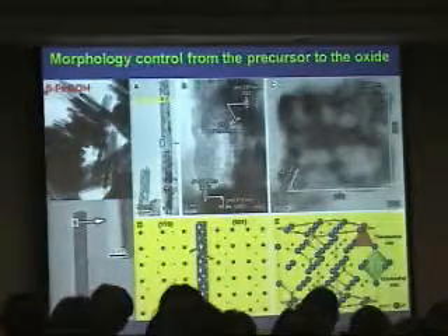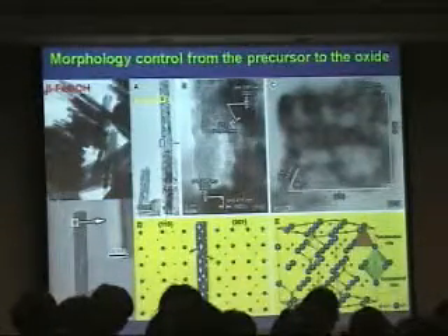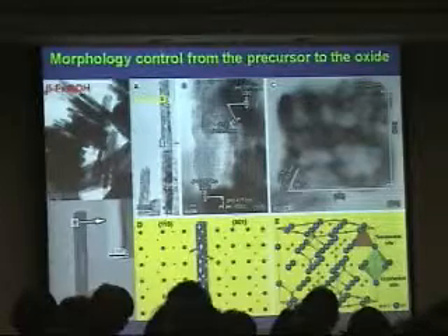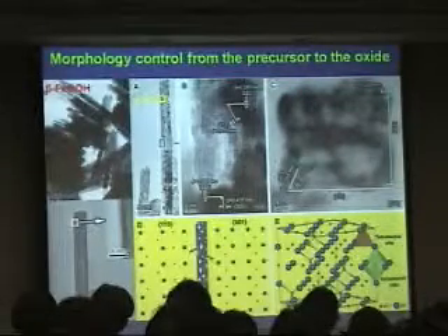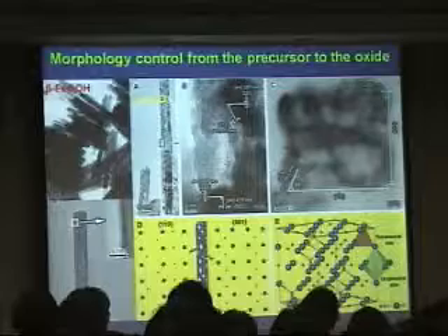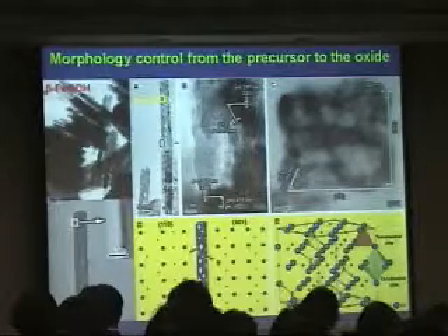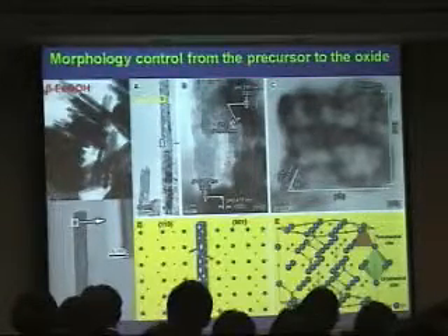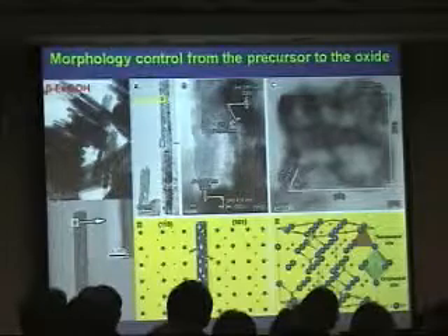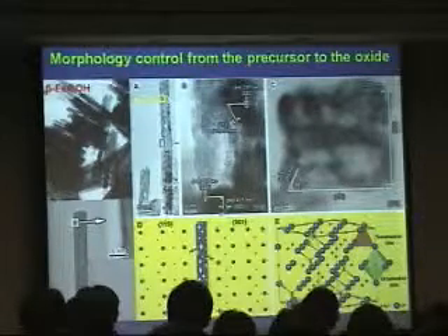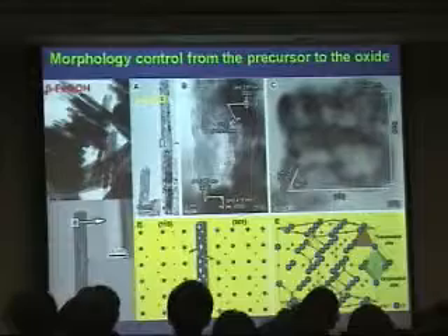And we get this iron hydroxide precursor followed by thermal treatment. So we get porous nanorods of iron oxide. And we can also have analysis for this side or the cross section of this nanorod. We determine the morphology like this. That means this nanorod exposes these two crystal faces and their coordination